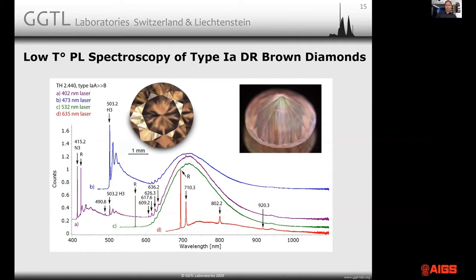This broad band has actually been found to be present in absolutely every single brown diamond that's type 1A. A type 1A brown diamond without this band is either extremely low in nitrogen, then the band might be undetectable, but all diamonds that have, let's say, more than 50 ppm of aggregated nitrogen, we have found this band, particularly strong in type 1AB samples, much less strong in type 1AA samples. This broad band is very likely the vibronic structure of either 617.6 or 626.30 phonon lines. These always occur together and correlate in intensity. It's quite likely that one or both of them are zero phonon lines of this structure.